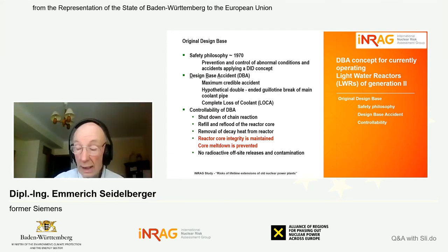Why 1,000 degrees C? At about 1,000 degrees C, the cladding of the fuel rods, which is a circular cladding, first will balloon, and will heat up more and more. That means ballooning fuel rods will block the sub-channels where the coolant should go upwards and cool the fuel rods and the fuel elements. And ballooning had to be prohibited in such a design-based case. So about 1,000 degrees is the limit where the core can rise up,